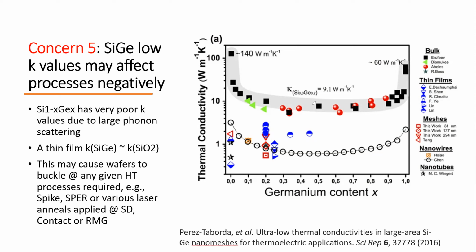Initially, you think this is an alloy, so you should do a straight line, just a linear extrapolation. So at 20% germanium, I should get like 100. Just eyeball it. No, the reality is there is a bell shape. It dropped very quickly like a rock. It becomes 10. At 20% germanium, you lost more than 90% of your conductivity.